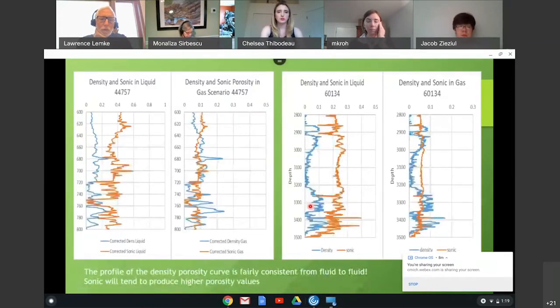We want to compare again how these curves look to each other. Are they similar? For the sonic porosity in the gas scenario, you have a lot of crossing over of density, and the sonic method produces higher porosity. So the density, if you look at this blue curve, the density curve looks pretty consistent no matter what fluid you're in, but again, the sonic porosity, especially in gas, can produce different results. So sonic is pretty sensitive and the gas fluid tends to change that.